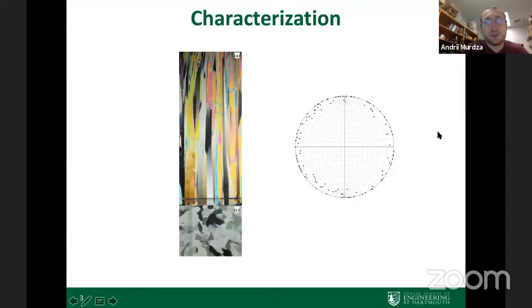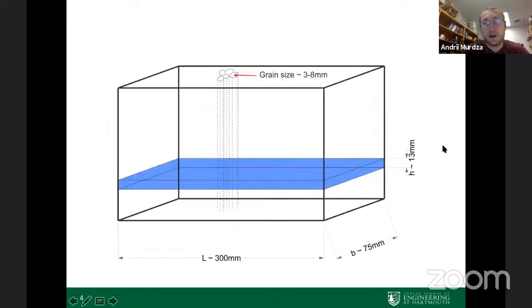So for this, we grew freshwater columnar S2 ice, and as you can see, the vertical and horizontal microstructure of the ice that we used as a parent material. The C-axis orientation confirmed that we indeed grew S2 ice. We had a block of ice with the columns oriented, in this case, vertically. The grain size was about 3 to 8 millimeters. And we prepared ice plates, as you see in this image in blue.